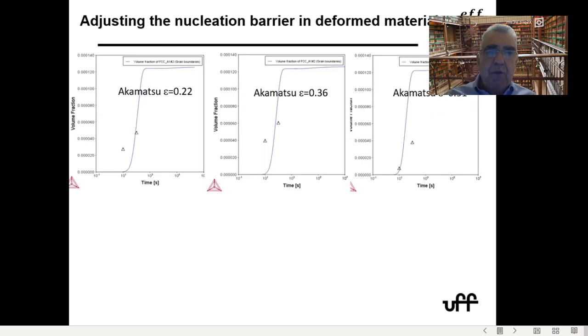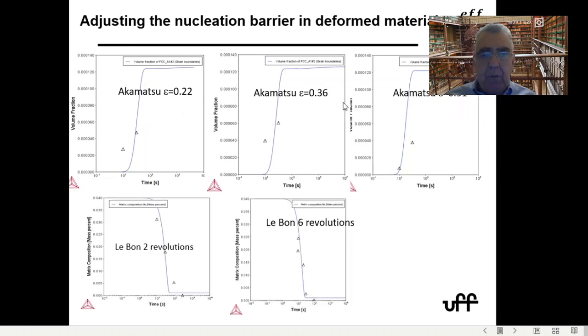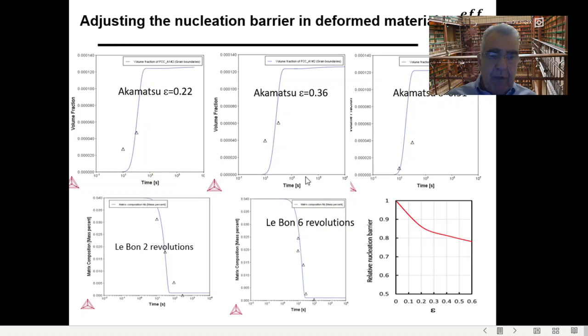So what we did was we created an effective nucleation barrier using an adjustment in the interfacial energy. So we got some classical results from literature about the effect of deformation on the precipitation of niobium carbonitride from various authors. And then we had the effect of the deformation on the nucleation barrier.